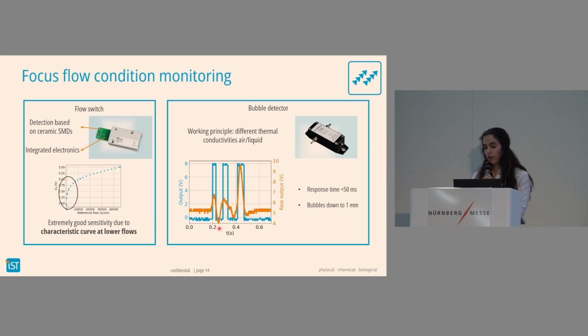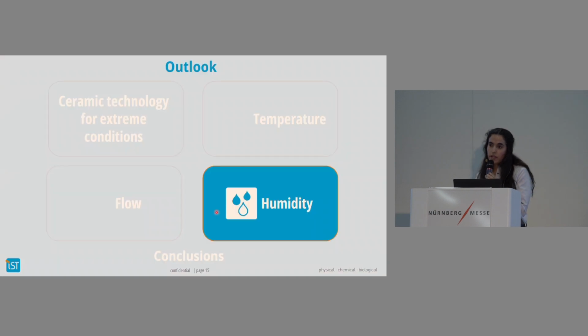The response time, as you can see, is also quite fast because here we have a scale that goes to below a second. And as you can see, it takes less than 50 milliseconds to detect the bubbles. That would be for flow.